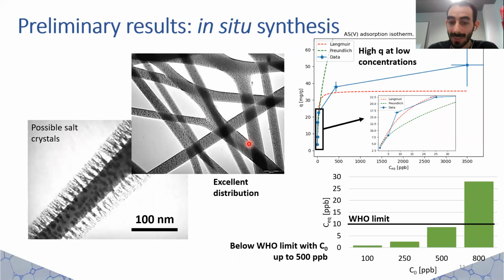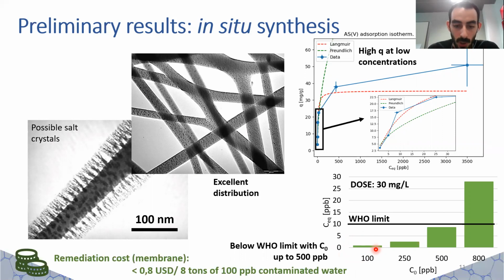The adsorption isotherm showed excellent results. We could lower the arsenic concentration of water from 100 micrograms per liter to less than 1 microgram per liter with an adsorbent dose of only 30 milligrams per liter of magnetite. Moreover, we performed a cost estimation which indicates that less than $0.8 can produce enough material to clean 8 tons of water contaminated with 100 micrograms per liter.